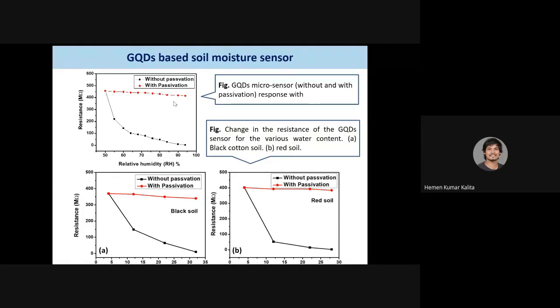That is the reason why we have used two types of sensors: the main purpose of the passivation is to check whether it is actually the moisture which is changing the resistance of the sensor. And it is actually the moisture, because without the passivation we can see the resistance decreasing, whereas with passivation the resistance remains the same. This resistance is basically the intrinsic resistance of the GQD without any moisture from the external media.